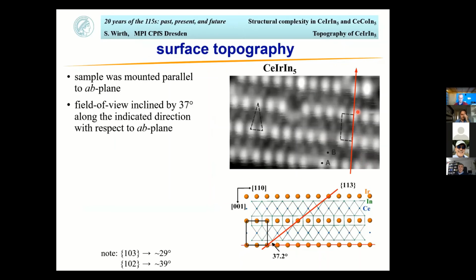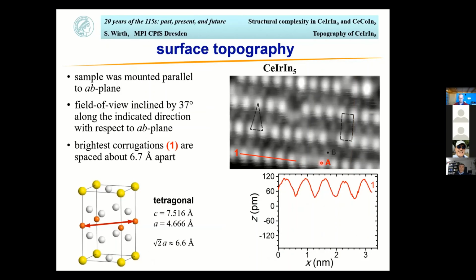Now, along this line, this red arrow here, what we actually saw was that the field of view is inclined by 37 degrees. So if you think of 37, that's quite a number. What's closest, which could give you a 37 degrees inclination, would be a 113 plane. Other planes with lower indices are the 103 or the 102, which are a little bit off. But I'll argue that what we are seeing is the 113 plane. Now I look along this direction here, which is not inclined at all. These brightest corrugations have a distance of about 6.7 Angstrom. If you look at the cell here, this corresponds to square root 2 of a, which is 6.6 Angstrom. So that's a pretty nice agreement. That fits very well.